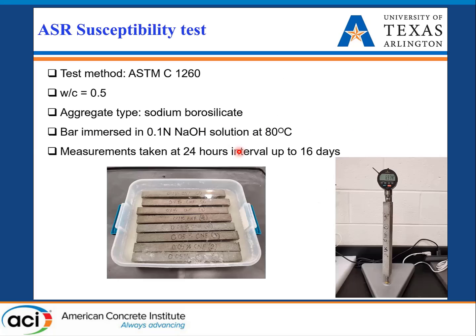We tested this using ASTM C1260. We prepared mortar with sodium borosilicate glass aggregate — a very reactive aggregate — and placed samples in sodium hydroxide solution at 80°C, which is a pretty harsh environment for ASR reaction. We monitored the expansion of mortar bars at 24-hour intervals up to 16 days, as specified by the standard.